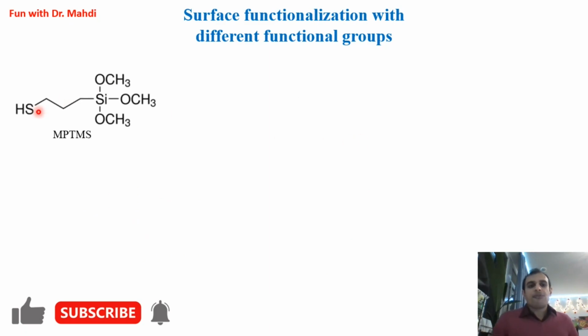For example, if you would like to do silanization, and if you would like to have thiol on the surface, it's better to use MPTMS, mercaptopropyl trimethoxysilane. But please note, mercaptopropyl trimethoxysilane is a liquid, and you don't need to use pure mercaptopropyl trimethoxysilane. Sometimes you need to make a solution 1% or 2% in toluene. I mean 1 milliliter MPTMS or 2 milliliter MPTMS in 100 milliliter toluene, and you need to leave your substrate, and after 3 hours washing you will have this compound on your surface.